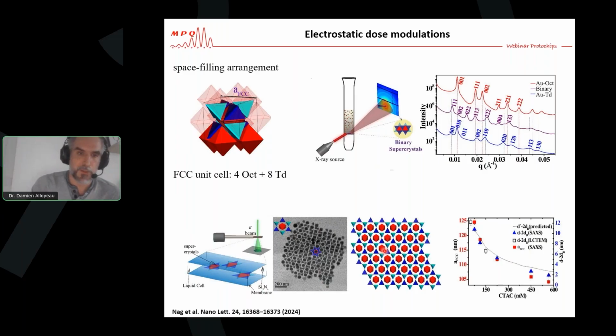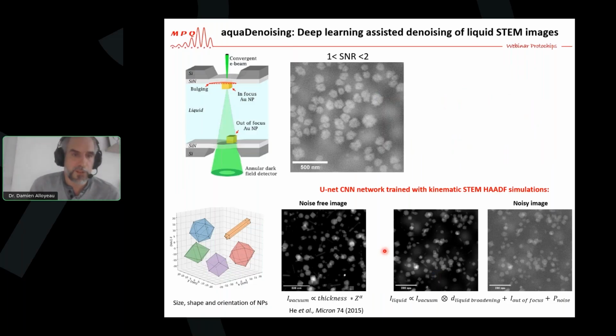And the last thing I want to show you is that sometimes you need to drastically reduce the electron dose rate. It's necessary for your experiment, and then you will not see anything anymore. So in that case, what we have developed is a deep learning assisted denoising of liquid STEM images. So we used a deep learning approach to improve the signal to noise ratio of liquid cell STEM images. So here I show you an example where you have gold nanoparticles in the liquid cell, and the main problem of this image is that our eyes are actually fantastic detectors.